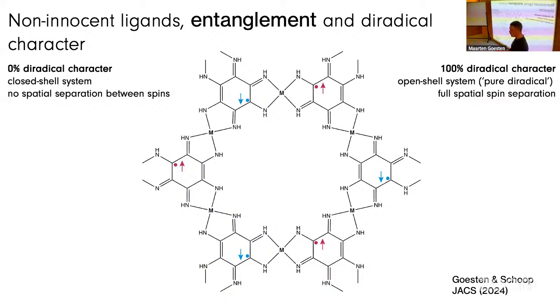So this is the idea of quantum molecular tectonics, combining this delocalized radical approach with space group theory. And this is a demonstration of the concept where we are now introducing platinum. At this point, this is a hypothetical MOF, but these complexes have all been synthesized with both palladium and platinum as well. So we believe this is possible. But what we try to do here is look at what happens when we introduce strong spin-orbit coupling so that we lock the momentum of these charge carriers onto their spins.